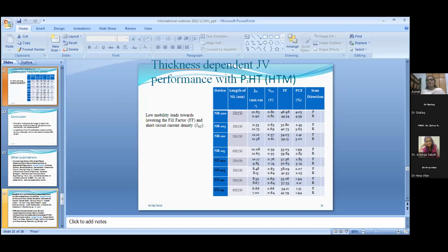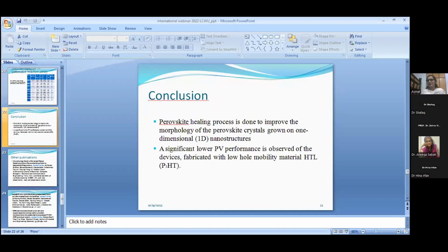Now we have the conclusion. The perovskite healing process is done to improve the morphology of the perovskite crystal structures grown on one-dimensional nanostructures. It means healing improves the morphology, and we also have greatly improved infiltration of the perovskite in the nanostructures. The second work was done to compare a low mobility hole material with a high mobility hole material. So we have a comparison between the spiro and the P3HT. We can see that a significantly lower photovoltaic performance was observed in the devices fabricated with the low mobility hole transport material.